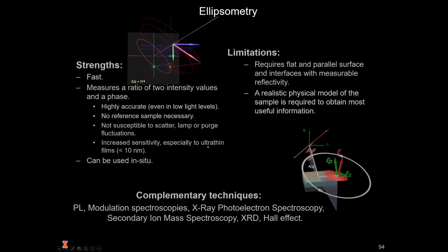So the strengths of ellipsometry reside in the great sensitivity it has to small changes in the dielectric function of materials. It's an ideal technique for measuring thin films and heterostructures with flat surfaces and optically accessible interfaces. Its main limitations are the need of a realistic model for the sample and the fact that it requires relatively flat surfaces and interfaces for accurate measurements.